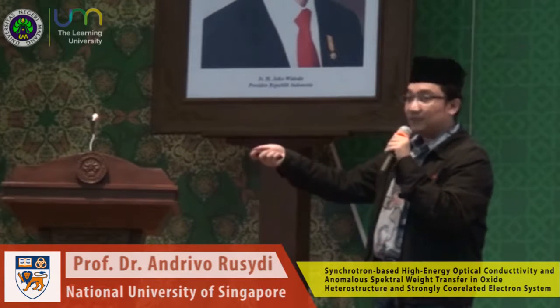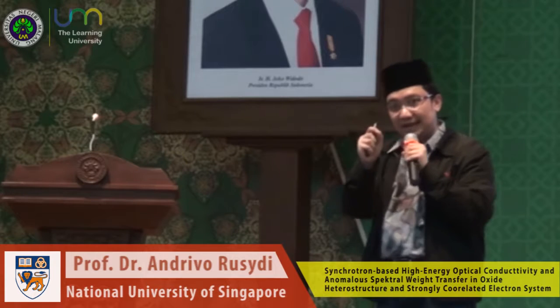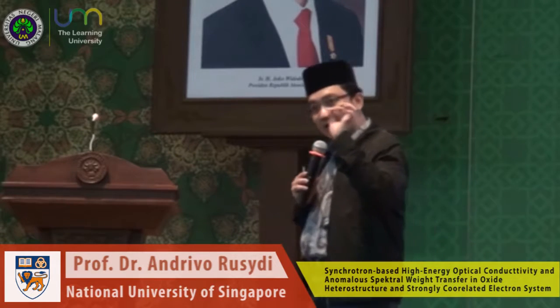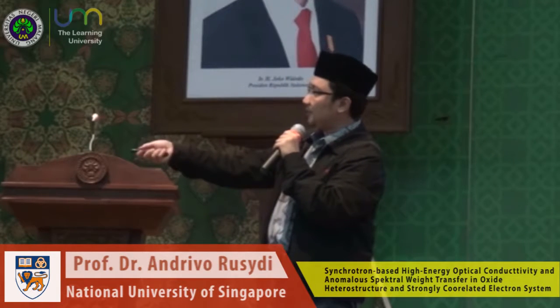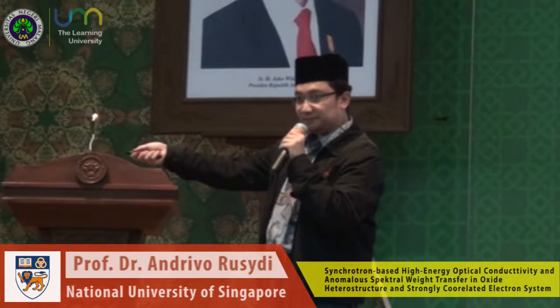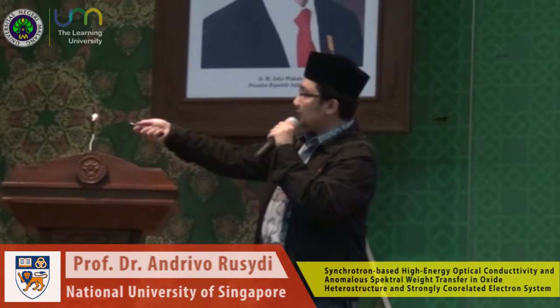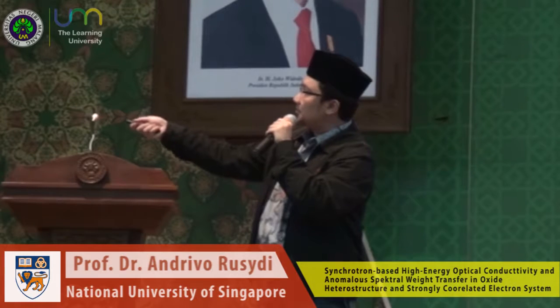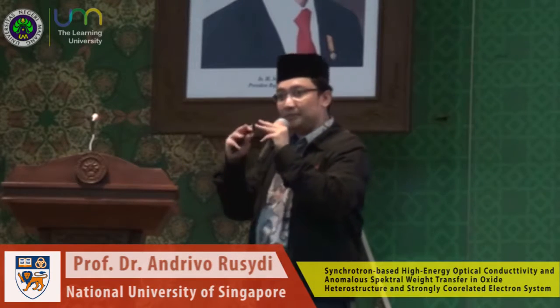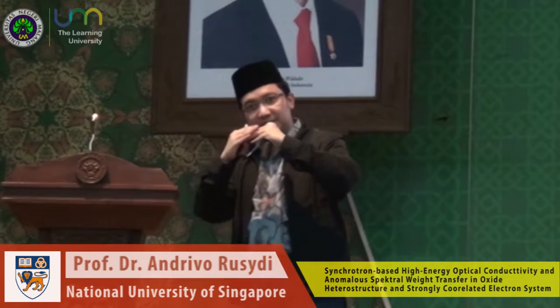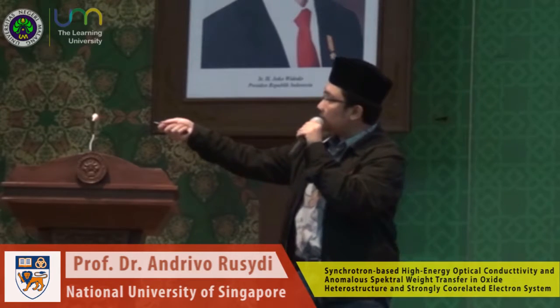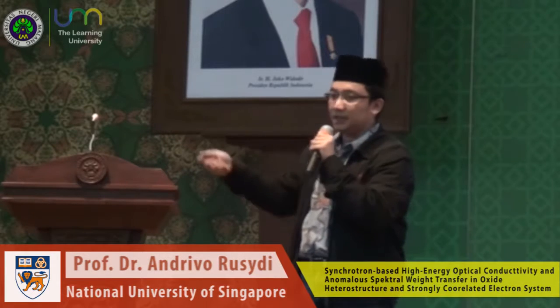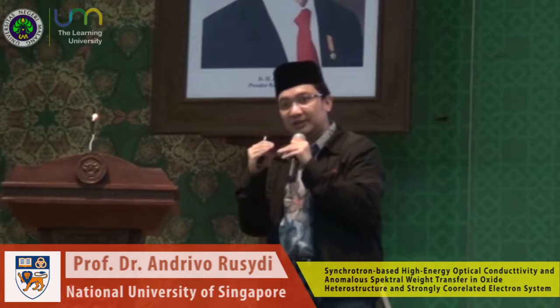If you look at this reflectivity, what you want to measure is electrons. One way to measure electrons is to measure reflectance as a function of energy. So the y-axis here is reflectivity versus photon energy, right? Then you make a comparison: this is bulk STO, bulk LAO. Remember, bulk means without adding both materials, so it's an independent material. And then you have 2-unit cell, 3-unit cell, 4-unit cell, 6-unit cell of lanthanum aluminum O3 on strontium titanium O3. Right, so you really control that number of units.